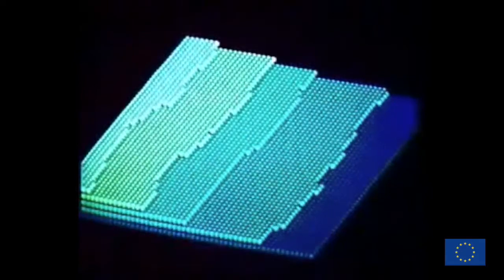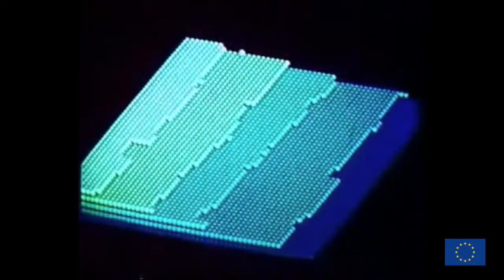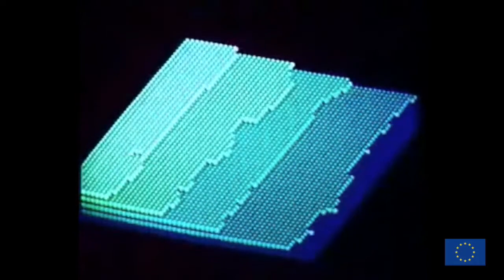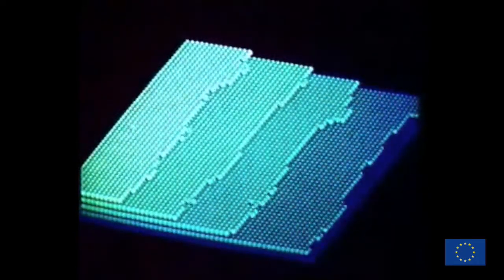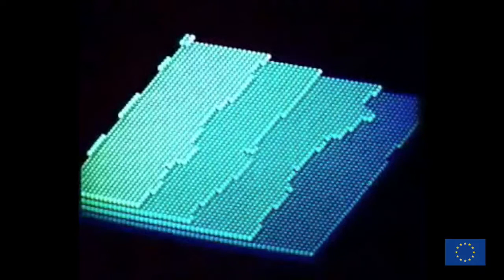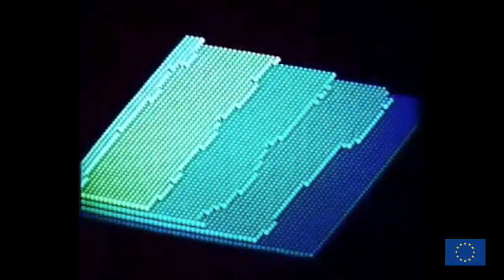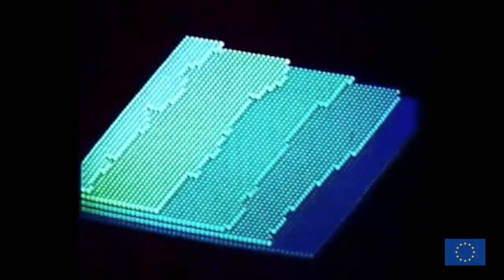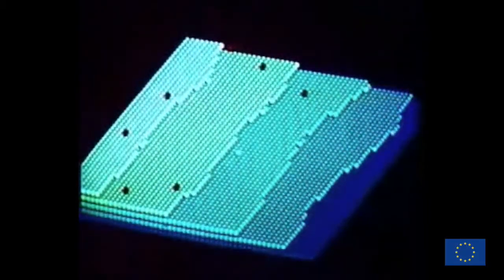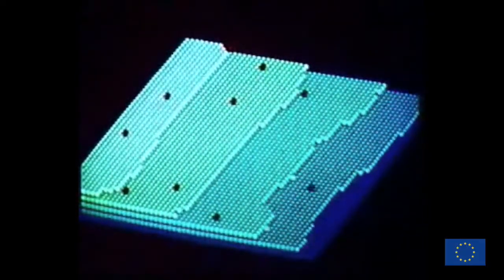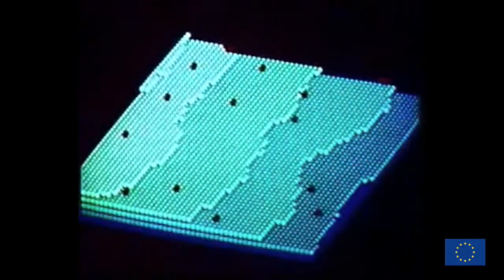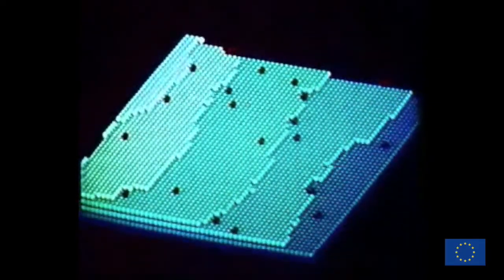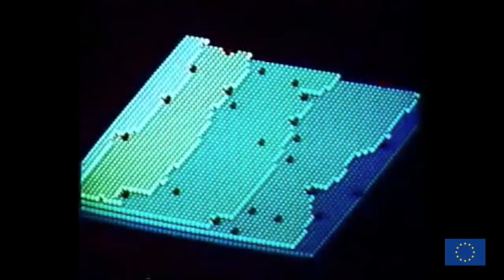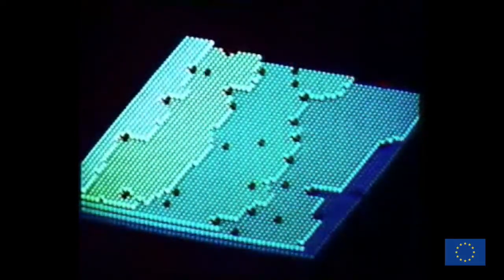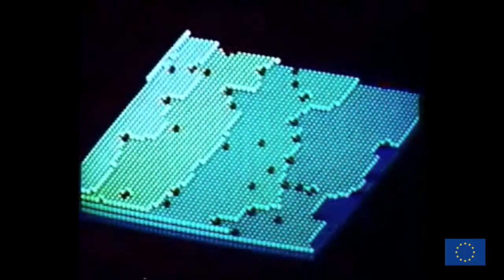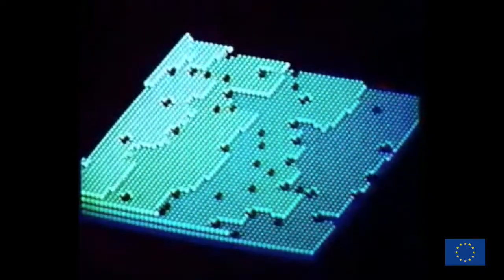So this is really what, as a crystal grower, you want to achieve, this step flow. Now, what will happen at a certain point is that, again, they will introduce contaminants into this step flow, which will be the black dots. They are coming now. And you should see how the black dots interact with one of these steps. So in between, your step flow just continues, but here at this one, it is really blocked. So the contamination really stops the propagation of this step flow across your surface.